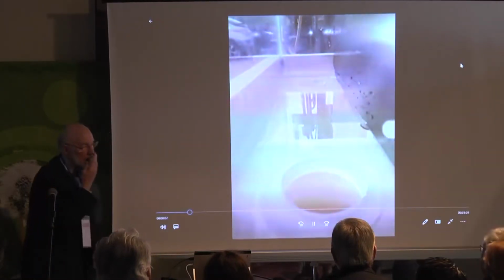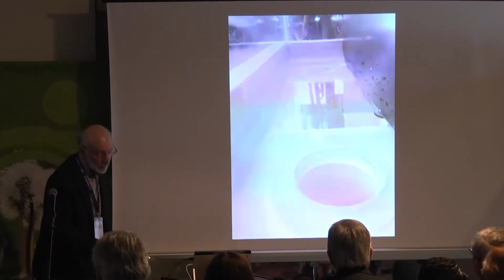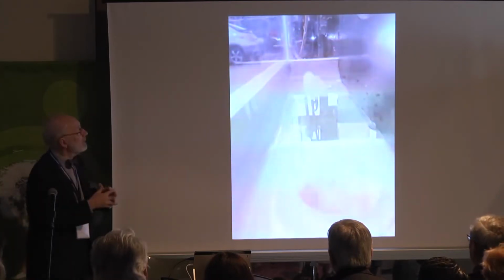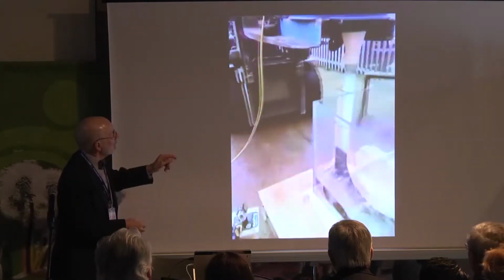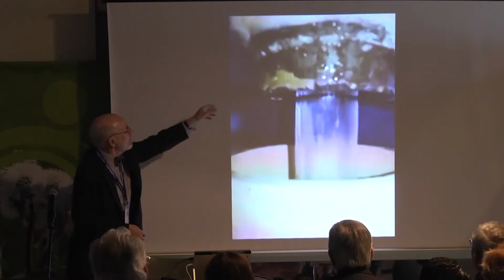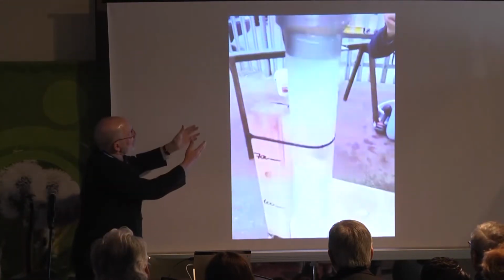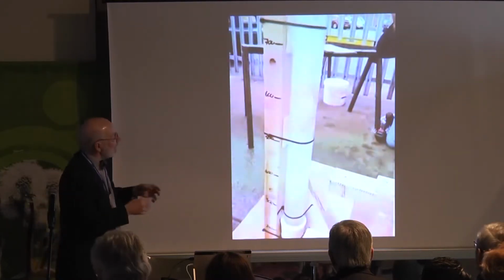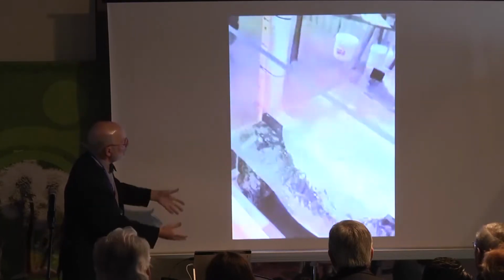Okay, I have it. This is a water model showing a conical basin and showing how we take air into the system. So here we've got 2 ingates, the metal's coming in. At the moment we'll have a look at, here is the nozzle from the basin, here's the metal going to the conical nozzle, and look at the metal falling and all that air churning away. And here's all the bubbles coming up.